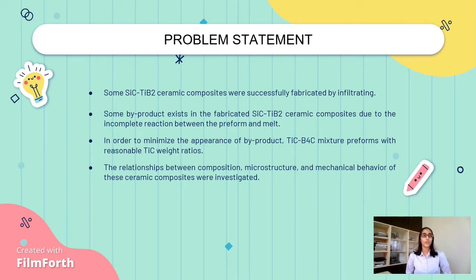Due to the incomplete interaction between the preform and the melt, certain byproducts are always present in the produced silicon carbide titanium diboride ceramic composite, which may be detrimental to their mechanical characteristics. In order to minimize the appearance of the byproduct, titanium carbide boron carbide mixture preforms with reasonable titanium carbide weight ratios were designed so as to synthesize pure silicon carbide titanium diboride ceramic composite.